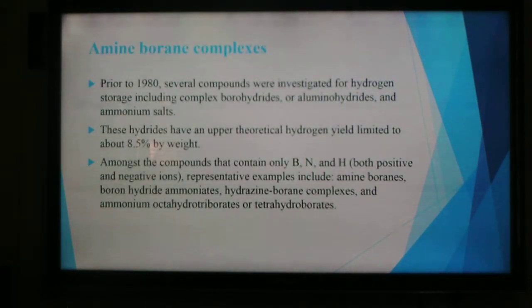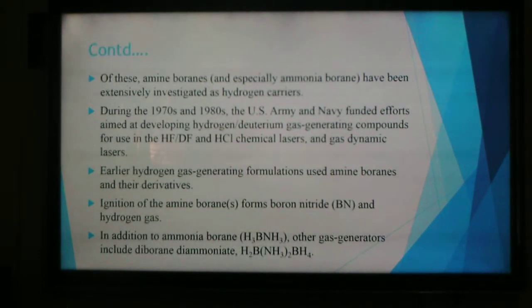There have been several compounds investigated for hydrogen storage, which are borohydrides, aluminohydrides and ammonium salts. These hydrides have upper theoretical hydrogen yield up to 8.5% by weight. Among these components, boron, nitrogen, and hydrogen representative examples include amine boranes. Of these amine boranes, especially ammonia borane, have been extensively investigated as hydrogen carriers. So ignition of ammonia borane forms boron nitride and hydrogen. In addition to ammonia borane, other gas generators include diborane diammoniate.